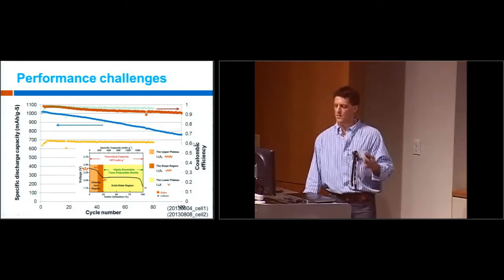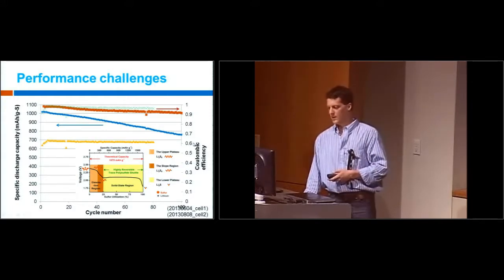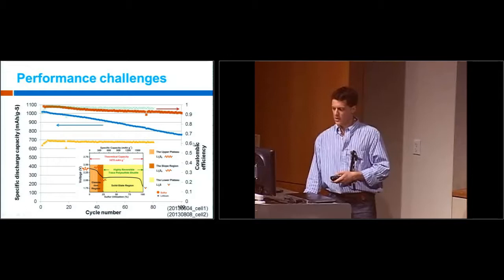And so you have something that resembles the current lithium-ion batteries, in that you're not going to have material dissolving and diffusing out of the cathode. If you agree to only cycle in this part, you lose nominally about 25% of your total capacity, but you have theoretically a much lower loss. So this is a comparison. This is the configuration where I cycle only along this lower plateau in the solid state region. You can see the capacity is lower than it is when I cycle through the full range, but that it's essentially constant.